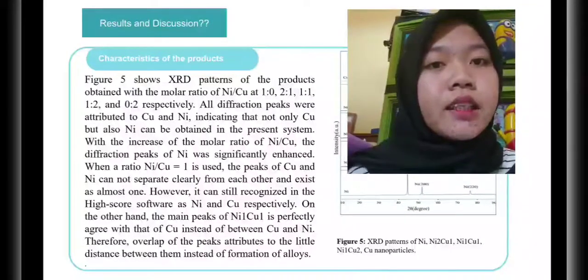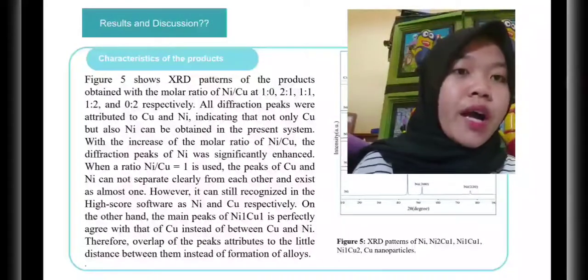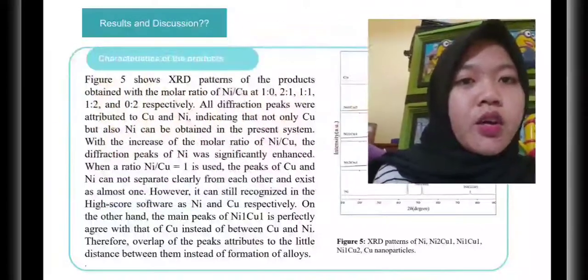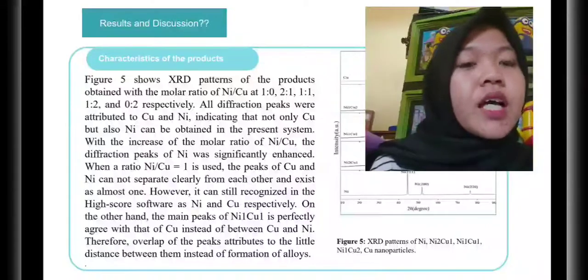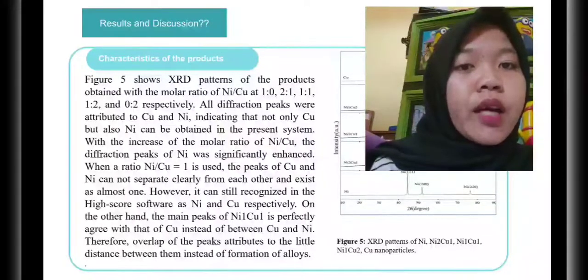Second, characteristics of the product. Figure 5, you can see it in my PPT, figure 5. Okay, figure 5 shows XRD patterns of the product obtained with the molar ratio of nickel to copper at 1:0, 2:1, 1:1, 1:2, and 0:2 respectively. All the diffraction peaks were attributed to copper and nickel, indicating that not only copper but also nickel can be obtained in the present system.